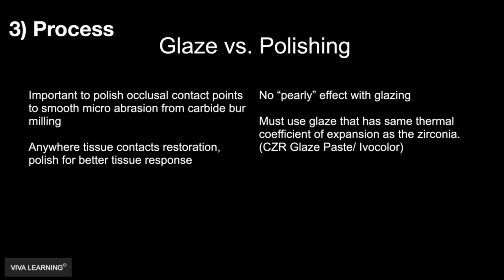So essentially, by polishing only, and we can pre-polish this in the pre-sintered form, not too hard, a very soft polish with some Meisinger, what's called twist polishing burrs. I typically don't like to polish in the contact area because it's a chalky material before we sinter it. I don't want to remove that contact and take too much. But polishing shows that it's better for the opposing surface, and also better for the tissue.